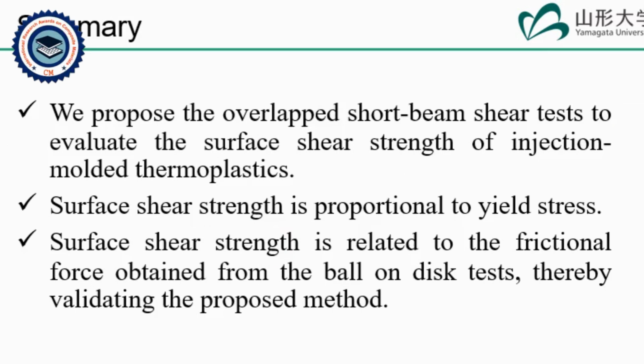In summary, we propose the overlapped short beam shear test to evaluate the surface shear strength of injection molded thermoplastics. Surface shear strength is proportional to yield stress. Finally, surface shear strength is related to the frictional force obtained from the ball on disk test, thereby validating the proposed method.